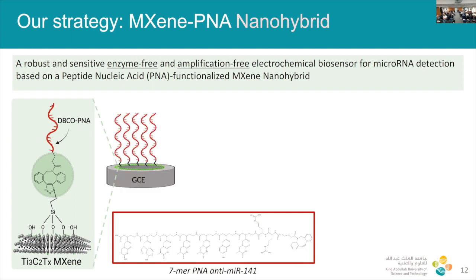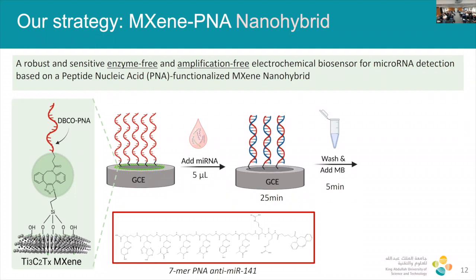And how does it work? Essentially, we drop the material on a standard electrode, a GCE electrode. So you have your PNA there, and then we add our biological fluid sample. In our preliminary results, this is just 5 microliters of microRNA. Of course, in the presence of your target microRNA, you get a specific hybridization. This is typically 25 minutes at room temperature. And then, of course, you want to wash off any non-specifically bound nucleic acids. And we add a reporter.